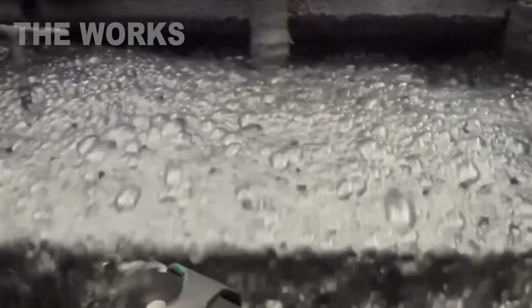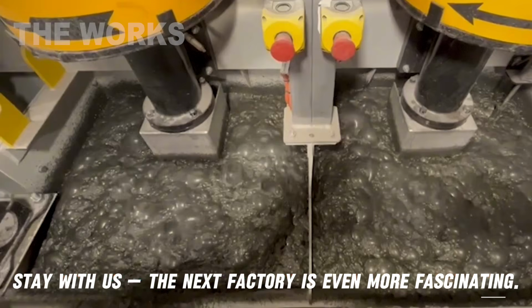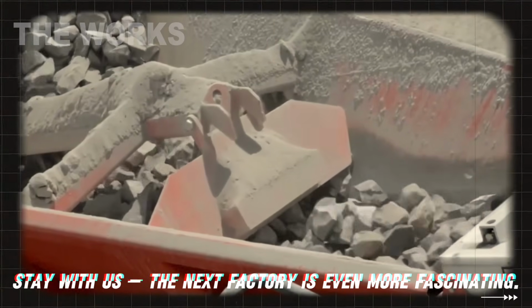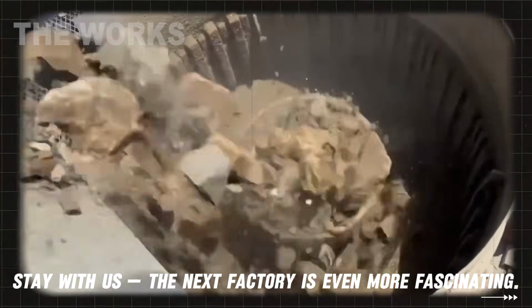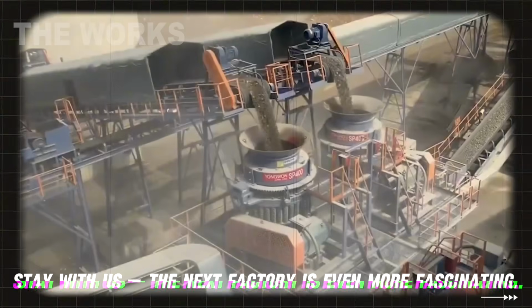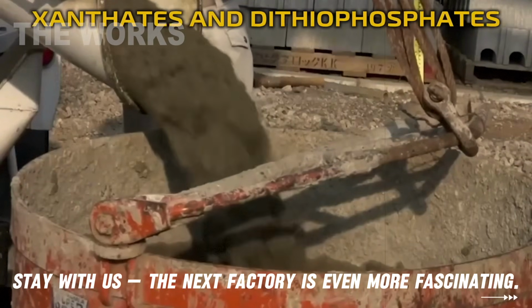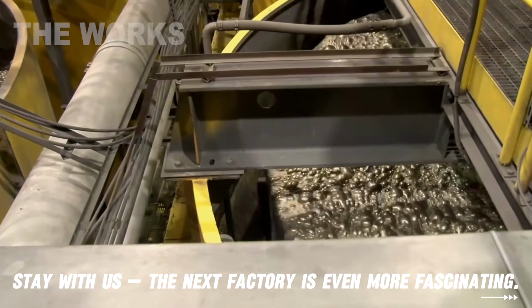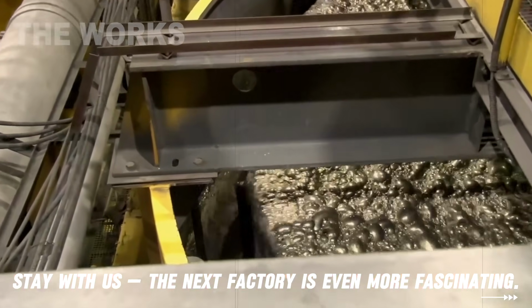The ore gets crushed, then goes through flotation. That's a process that separates minerals based on how they stick to air bubbles and water. Mills grind the ore down until 60% of the particles pass through 75 micrometers. Then the ground ore gets mixed with water, and collector reagents are added, things like xanthates and dithiophosphates, which make the sulfide minerals containing platinum hydrophobic. Water repelling. Air gets pumped through the mixture, creating millions of tiny bubbles. The hydrophobic particles containing platinum stick to the bubbles and rise to the surface, forming a froth that gets skimmed off.